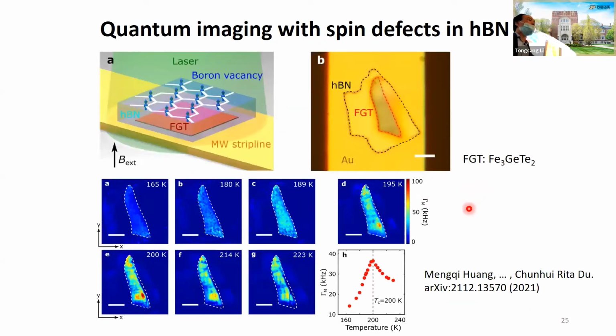Then recently there's a paper posted on arXiv from Chunhui Du's group in December 2021. They also put hBN on a gold waveguide and basically use the same scheme as we did. But in addition to hBN, they put a 2D magnetic material, FGT, iron germanium telluride, and use hBN as a quantum sensor to image it. You can see this scale bar is 5 micrometer. When the temperature is low, it is a 2D ferromagnet, and when you increase the temperature, it eventually becomes paramagnetic. During the transition, they can see the structure and also observe spin fluctuations, and the change of the T1 of the electron spin caused by the spin fluctuations. So this uses hBN for quantum imaging of 2D magnetic materials.